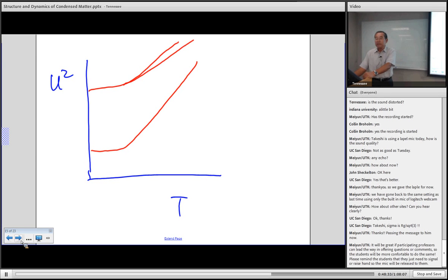Quite often, you see a U value much bigger than 0.1. For phonons, you can calculate the amplitude at low temperature. I just said 0.1, but it depends on materials. Okay, usually of that order, but it's not the same from one to the other. But you can calculate that, and I'll do that when we discuss phonons, how to calculate this amplitude. So compared to that, the measured U can be larger. We run into this all the time.